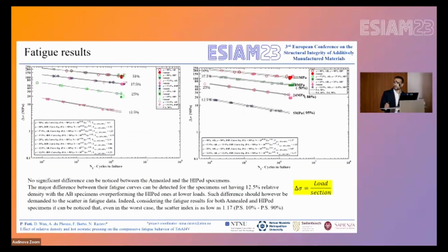Going to the fatigue test results, as we can see here, there is almost no difference between the HIPed and the annealed components. And indeed, if we consider just a unique fatigue curve for both the annealed and the HIPed components with the different relative densities, you can notice that we are able to summarize them with a quite narrow fatigue scatter band. Indeed, the highest value of the scatter index that we achieved is just 1.2, with probabilities of survival of 10 and 90%.